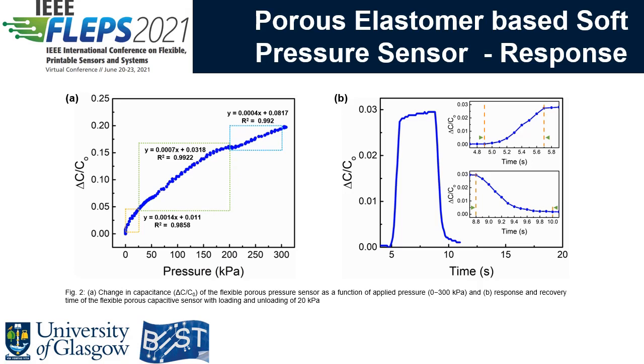Figure 2b presents the capacitive sensor's response in recovery time with loading and unloading of 20 kPa. When pressure was applied, the sensor's response time was 0.8 seconds, as can be seen in the top inset of Figure 2b. When the pressure was removed, the sensor's capacitance decreased with a recovery time of 1.2 seconds, as can be seen in the lower inset.